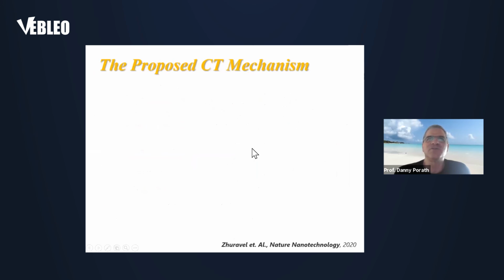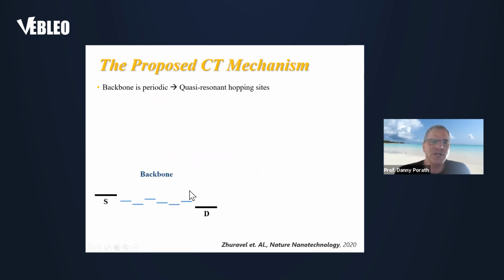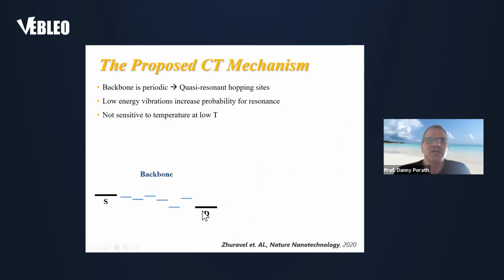It must be some kind of hopping, but not the thermally activated hopping that we were looking for before. So when we try to understand the meaning of the results, we can see that the backbone is periodic. So we have nearly similar states because of the structure, the physical distortion, and the temperature. There might be some small difference between their positions. So when we raise the voltage and we open some kind of a window here, the temperature causes some kind of resonant hopping through the backbone states from one side to the other.